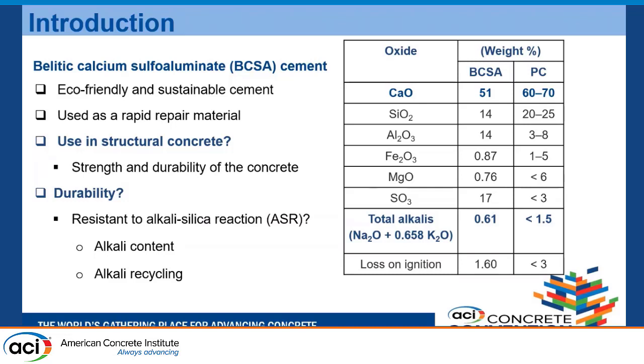So the question that needs to be answered is: is BCSA resistant to ASR? For that, we have two things that need to be looked at. One is the initial thing, that is alkali content, and the other is alkali recycling. For alkali content, the cement has to have less alkali, so it supplies less alkali for the reaction, and you hope that less alkali means less ASR in the concrete. The table on the right has a comparison of the oxide composition of BCSA and Portland cement. What we need to look into is the total alkali content. For BCSA, it's less compared to the typical Portland cement composition, which is a good start.